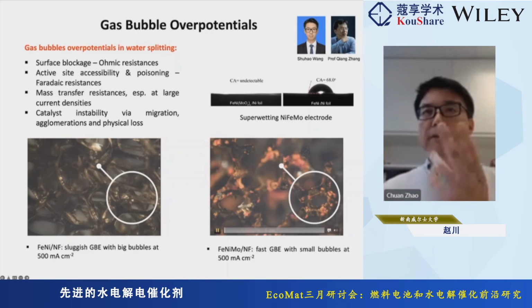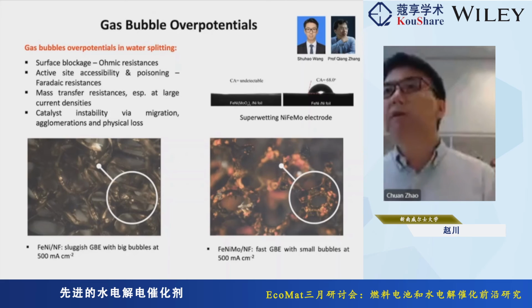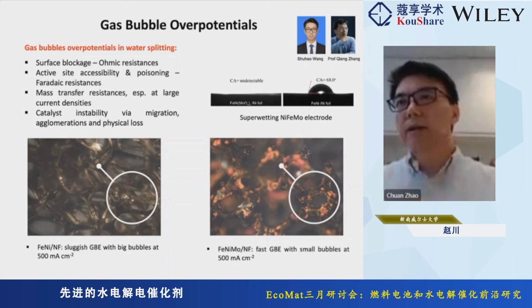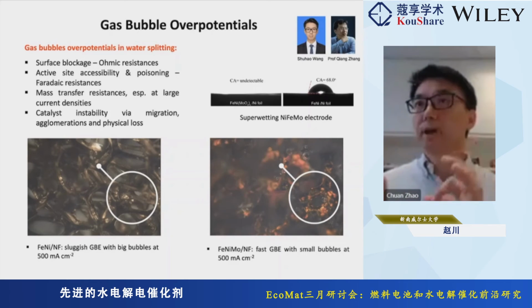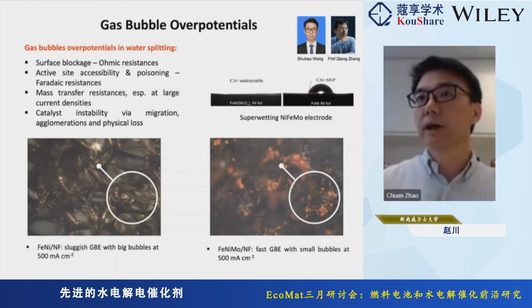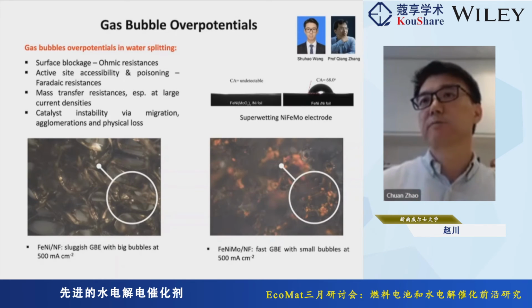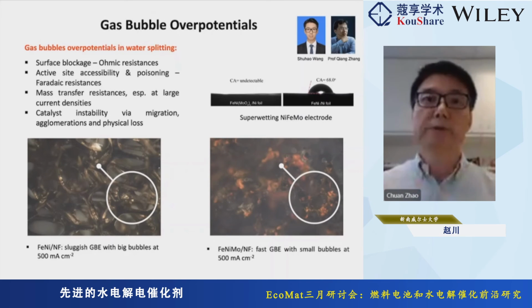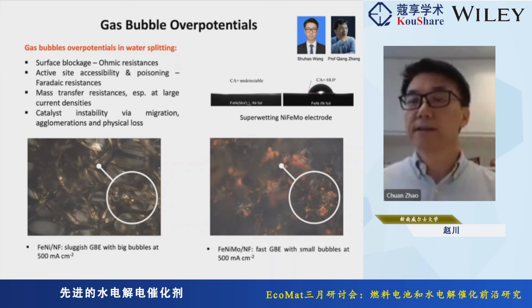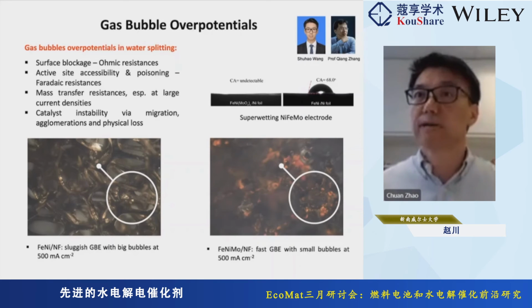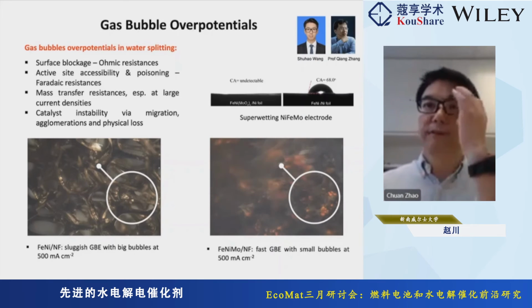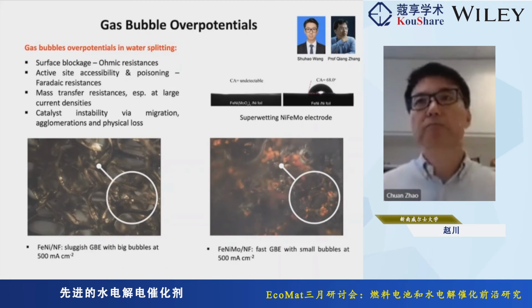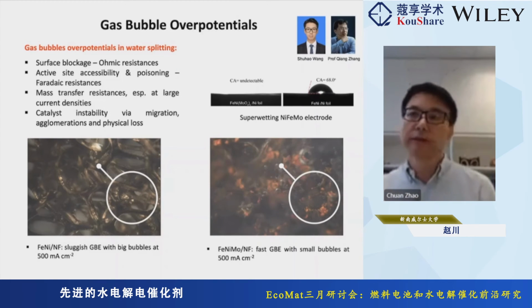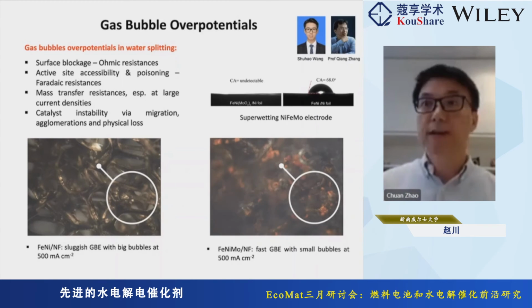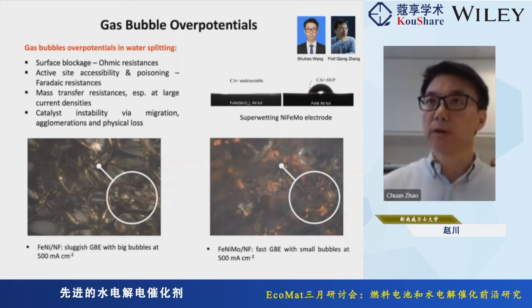But in comparison, when we have our nickel iron molybdenum, we can also see the gas bubble evolution is a lot stronger. The gas bubbles are a lot smaller, and detachment is happening at a much faster rate. I have to emphasize the two videos were recorded at the same current density. That means the same amount of gas is produced. But with the molybdenum modified one, the gas bubbles are a lot smaller and faster.